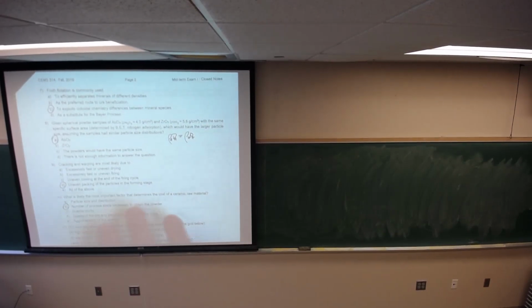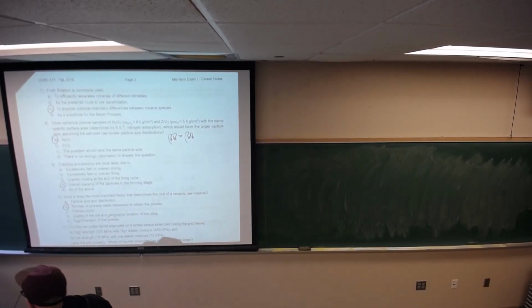Spherical powder, what you have is surface area is equivalent, so rho of A times D of A is equal to rho of Z times D of Z. Okay, so when you do that, since the density of aluminum is less than the density of zirconia, then the size of the aluminum must be bigger. It says, which would have a larger particle size, it has to be the aluminum. On my exams, the 4th answer here, not enough information to answer the question, is almost never the answer. By the way, in case you're wondering.